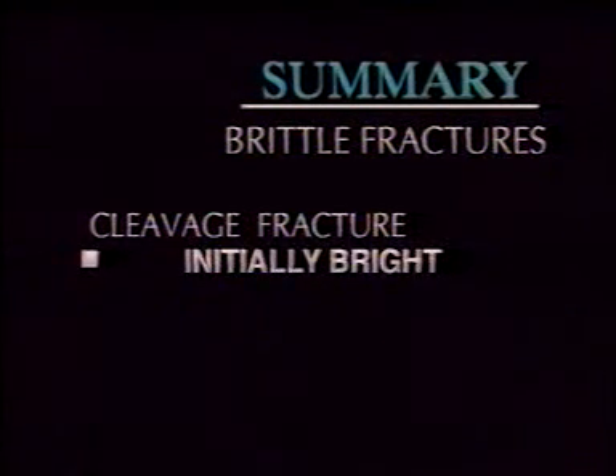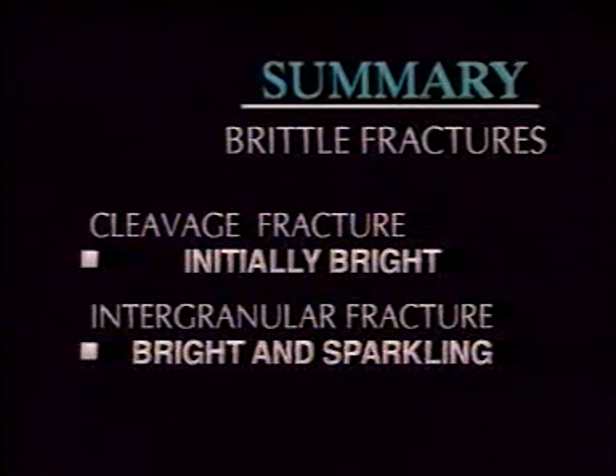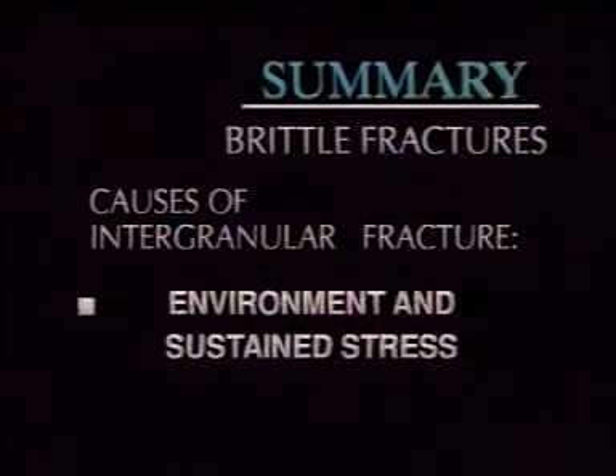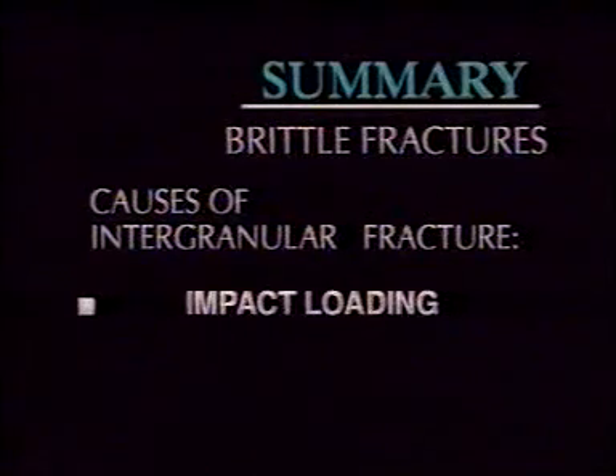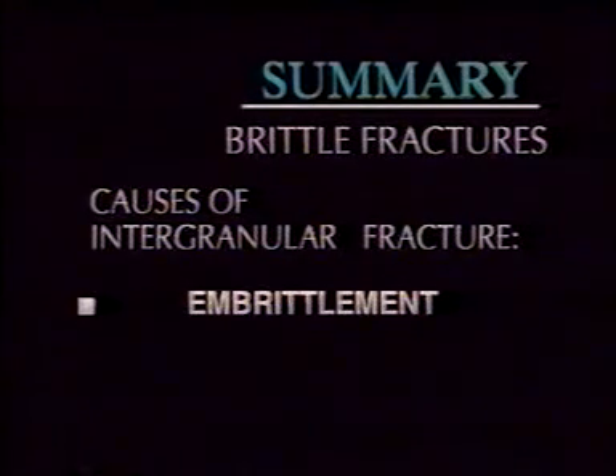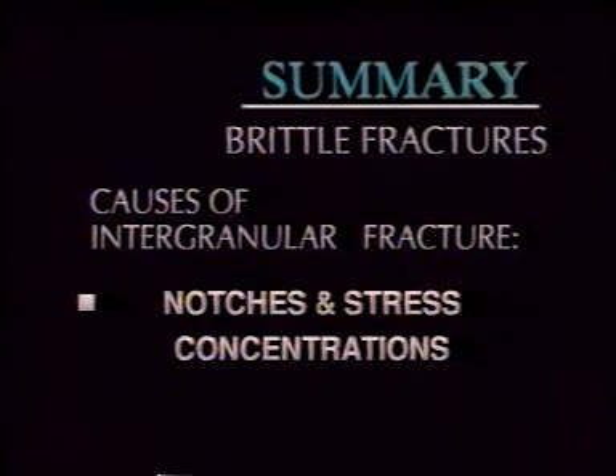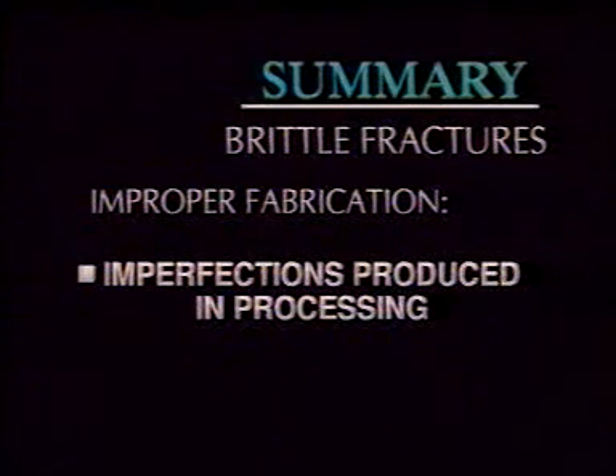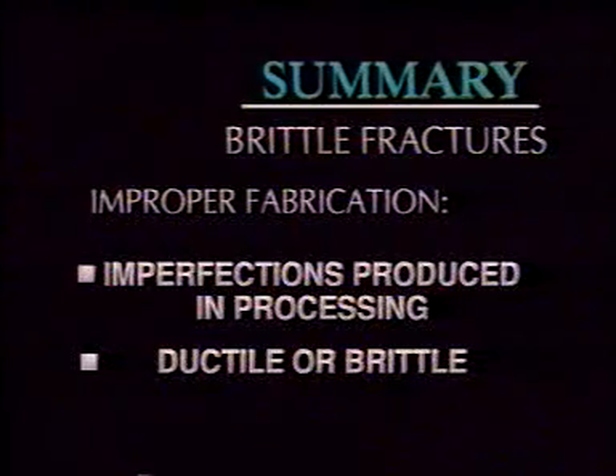Cleavage fractures appear bright initially. Intergranular fractures appear bright and sparkling like rock candy. Intergranular fractures are promoted by the cumulative effect of environmental factors and sustained stress, or by grain boundary embrittlement resulting from a number of different metallurgical phenomena. Many forms of embrittlement can lead to intergranular fracture in steel. Most often, the initiators of brittle fracture are discontinuities, notches, and stress concentrations. Failures from improper fabrication are caused primarily by the imperfections produced in parts during processing. These can lead to either ductile or brittle fractures.